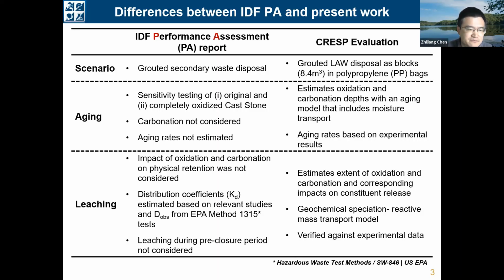And for the leaching of the cast stone in the report, the impact of the oxidation and carbonation on the physical retention ability of the cast stone was not considered. And also the distribution coefficient, or the Kd value of the contaminants, was estimated based on some relevant studies, and also the observed diffusion coefficient from the EPA Method 1315 test results. And also the leaching during the pre-closure period was not considered in the report. In this work, we estimated the extent of the oxidation and the carbonation, and also their impact on the contaminants release rate. And also we developed a geochemical speciation model together with a reactive mass transfer model to estimate the contaminants release rate. And the developed model has been verified against experimental data.